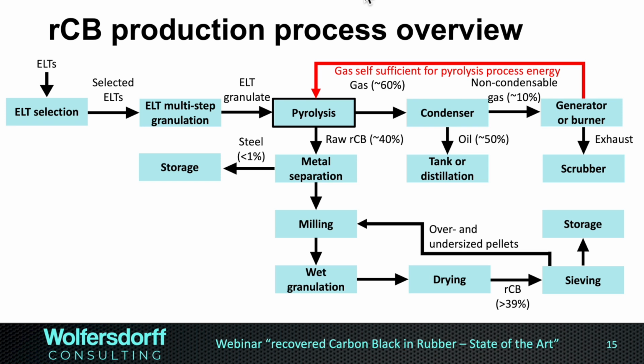Rubber is an insulator. Most of the pyrolysis reactors are heated from the outside, so we need a long time to heat the rubber. Microwave pyrolysis that could heat the rubber granules from the inside is not yet that much developed. And then we typically have a mass balance. We get gas out and we get the solid out. The gas typically is some 60%, and the raw recovered carbon black, the solid, is typically some 40%. Then when we follow the gas stream, the condenser really is important for the pyrolysis. The condenser separates the condensable gas from the non-condensable gas.